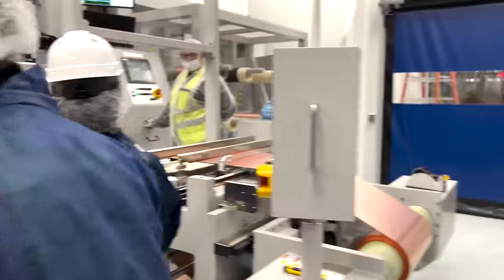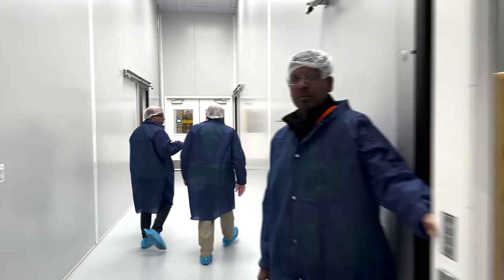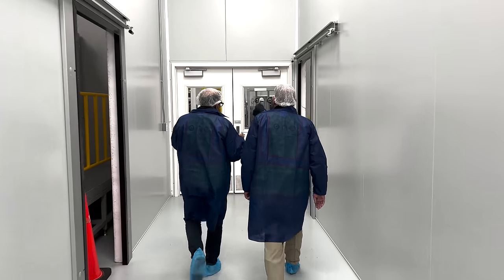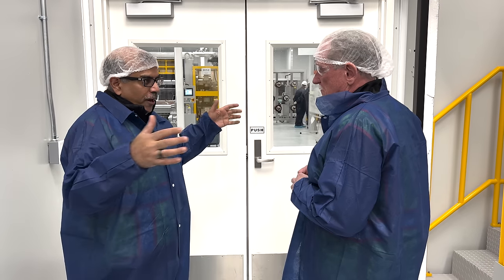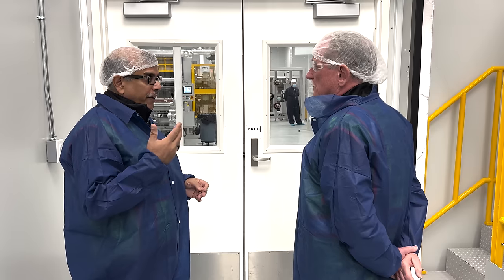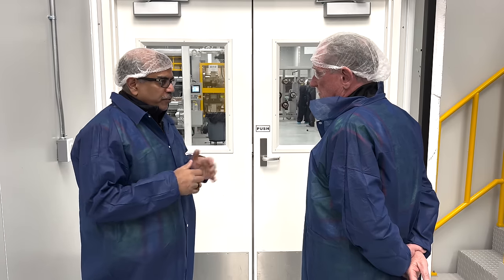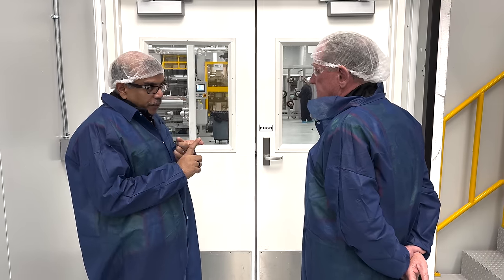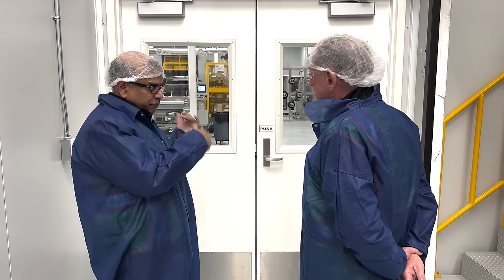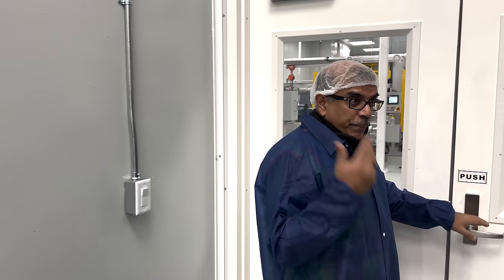The systems I saw in China were huge in comparison to this, so I'm hoping this is a pilot meant to be in low volume. Everything is kind of micro scale, and there's a reason for that. When we do a pilot factory, we're qualifying new materials. Those new materials sometimes are not available in massive quantities because you've got new suppliers you're bringing up. So you make the coating and mixing small enough that you can take maybe 20 kilograms of material instead of buying a metric ton, then you qualify it. The pilot is always done for a battery factory — it's the way you prove your suppliers and your cell design. This factory will make 10,000 cells in a month, enough to validate the product, get the design right, get the suppliers right, then we build the gigafactory.